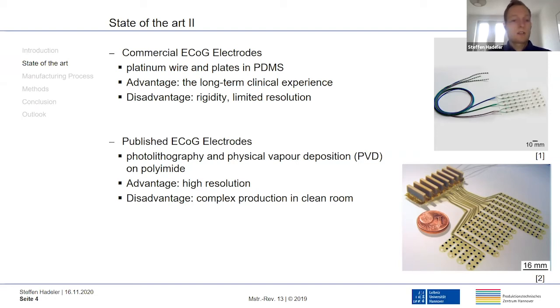So there are various research groups working on high resolution electrodes, but these are mostly produced by photolithography and physical vapor deposition on polyimide. One example can be seen on the right. The advantages of these electrodes are the high resolution and the small electrode spacing, but the disadvantages are the complex production in a clean room and the lack of long-term clinical experience compared to PDMS.